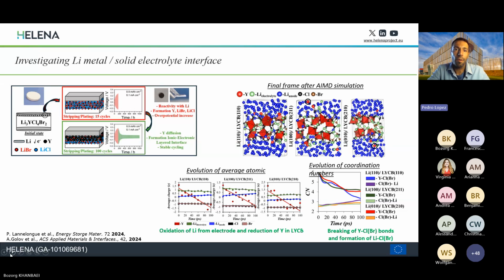So we observe from experimental symmetric cell cycling that the halide electrolyte was showing a reactivity with the lithium metal that was evidenced by an increase of the overpotential during the cycling, as you can see here on the pink curve. There were potential increases during the first hours of the cycling, and then it decreased and was stable, lasting up to above 1,000 hours.